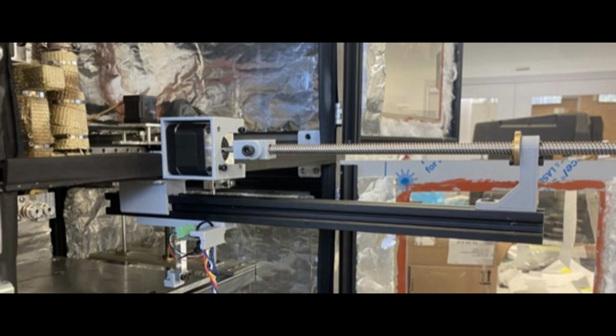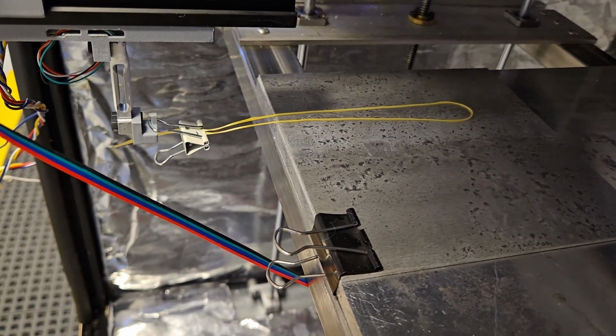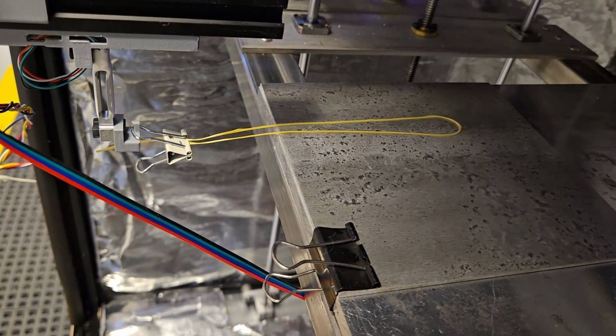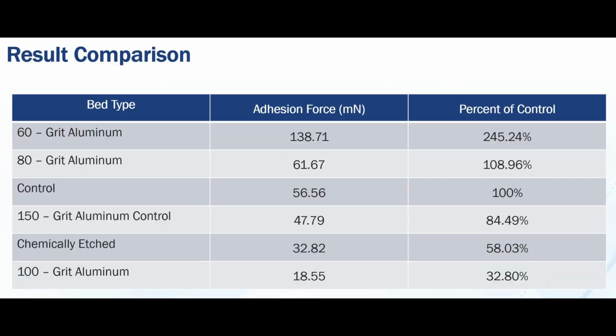We created an apparatus to test the force required to break adhesion from the plates and attached it to the printer. Here we can see an example of how our tests were run. Once that first slip occurred, we knew that the adhesion had been broken and recorded that value from our apparatus for further calculations. From our experiments, we found that our theory was indeed correct. Our highest surface area had an adhesion force more than double that of a regular plate.